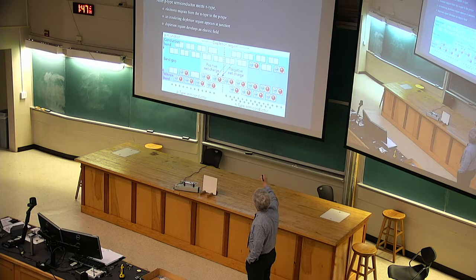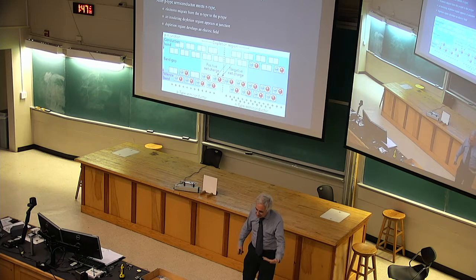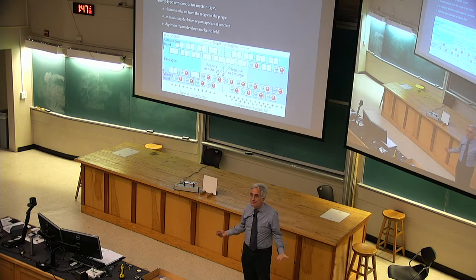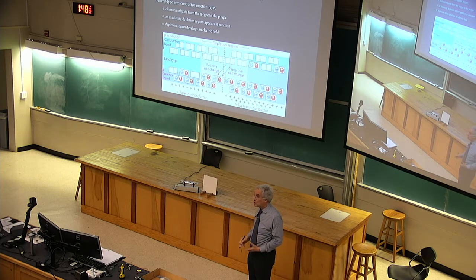And they leave the conduction levels and enter the valence levels of the other side. So they leave the conduction levels of the n-type semiconductor and enter the valence levels of the p-type semiconductor, a process that releases energy. And they will continue to do this until they have built up a significant electric field in this middle part. As negative charges leave the right and end up on the left side, the left develops a net negative charge, and the right side a net positive charge, so there's an electric field there. It's like a little capacitor.